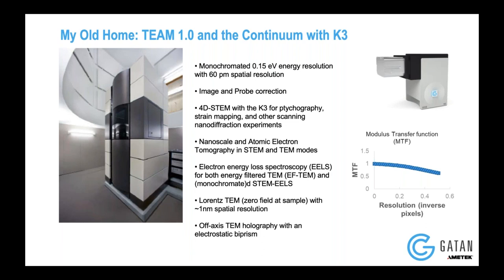You can see the modulus transfer function for K3 — it's absolutely fabulous, which means that it actually counts every electron. Especially for sensitive materials where the electronic effects are subtle, K3 can be very useful. In addition to that, the microscope also has Lorentz TEM and off-axis holography because it's also chromatic aberration corrected, and it's one of the only microscopes in the world corrected for chromatic aberration.